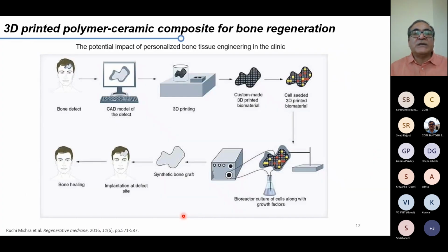So we looked into that. What you typically do with printing, taking whatever damage has happened, for example in the skull, is take a CT scan, make a CAD design, and print the scaffold. The good part is that you have calcium-derived inks, you have hydroxyapatite. We develop these in-house ourselves and make the scaffolds out of that, honeycomb-type structures. The structure, design and shape can be completely tuned by this CAD design. You can make it thickness-wise and shape-wise exactly mimic the individual patient. It is a more personalized type of graft construction.